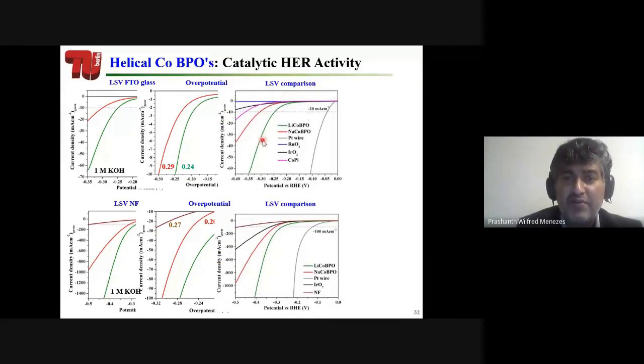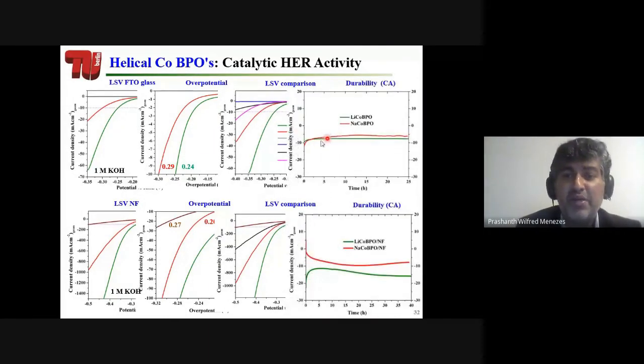We also compared with other catalysts, the noble and non-noble, but what we see is that platinum is the best catalyst for hydrogen evolution reaction. However, one should remember that this system doesn't work for oxygen evolution reaction. Still, we are the winners because we have oxygen evolution and also we have hydrogen evolution reaction with our catalyst. Similarly, the stability at 10 milliamp, that is minus 10 we tried, and we see that they are very, very stable. And we even get increased performance.